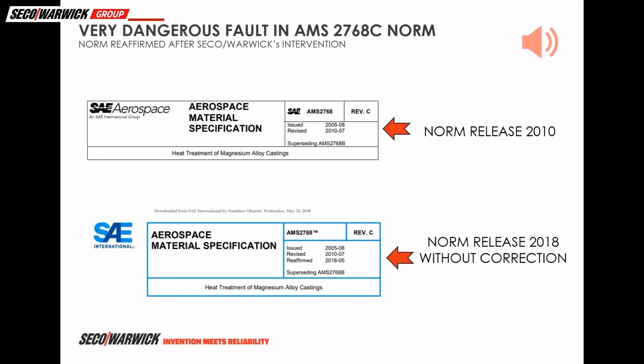Therefore, when we completed the investigation and summarized the results of our research, as the next step, we sent them to SAE International and NFPA, recommending changes to the AMS 2768C standard. We have reported a very serious fault with the recommendation of nitrogen as an extinguishing gas for magnesium alloys heat treatment. We also noted that many of the devices in use should be redesigned for safety reasons. As a result of our intervention, SAE called a meeting to analyze our results. However, no corrective action was taken yet.